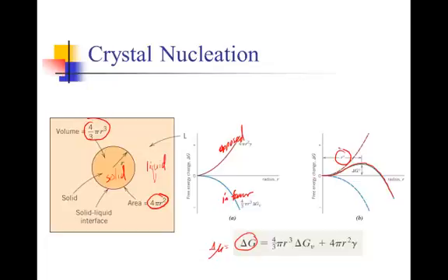And so that takes some time, and it has to be at the proper temperature. It turns out that materials will not crystallize exactly at their melting point or their freezing point. There's not enough chemical potential drive to overcome that surface energy. And so they actually go to a little bit below their freezing point before they start to crystallize.